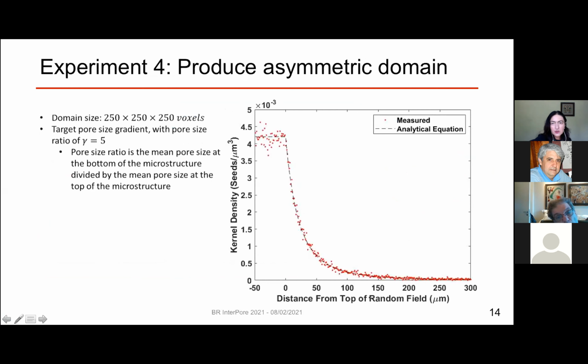So our fourth experiment is we wanted to see if we can produce an asymmetric domain. And here we have showing control of microstructure that produces an approximately linear pore size gradient with the ratio of 5. And the pore size ratio is defined as pore size on one end of the domain that is 5 times bigger than the opposite end. So on this axis, we see the kernel density.